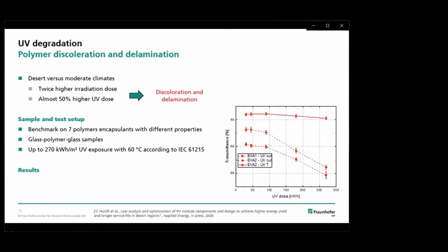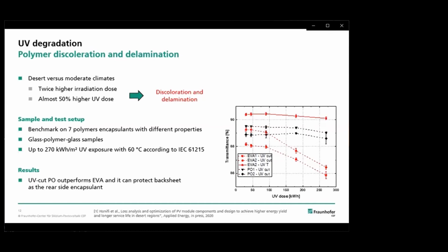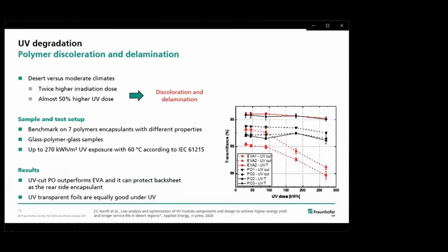And this was, for example, not the case if we had a UV transparent EVA. In comparison, we also looked at polyolefin, and for those, the polyolefin with UV cut properties didn't show any significant changes, and the same was also true for the UV transparent polyolefin. In conclusion, the UV cut polyolefin outperforms the EVA, and it can protect the backsheet, for example, as a rear side encapsulant, and the UV transparent foils are all equally good concerning the UV.